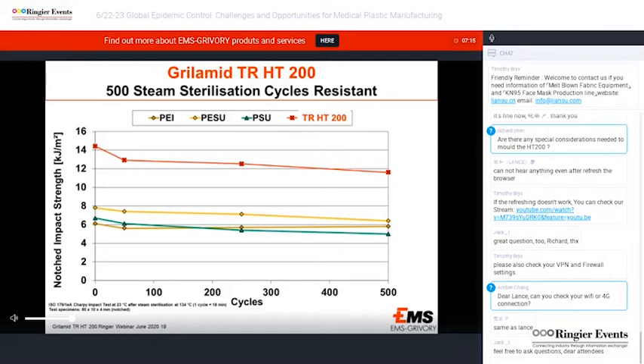At the steam sterilization cycle start, we see a slight dip over the first 50 cycles, after which the curve flattens out again. After 500 cycles, we can see that we still have an impressive 12 kilojoules per meter squared notched impact value, basically showing us that the steam sterilization process does not have any significant negative effect on the mechanical properties of the Grilamid TR HT 200, even after 500 cycles.